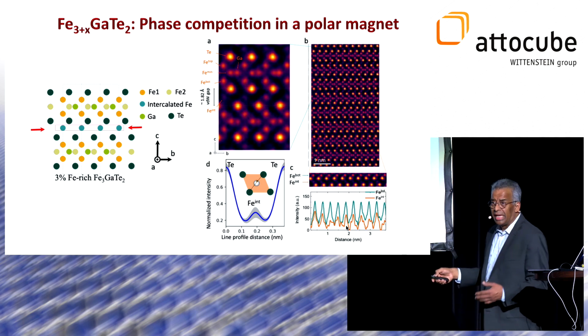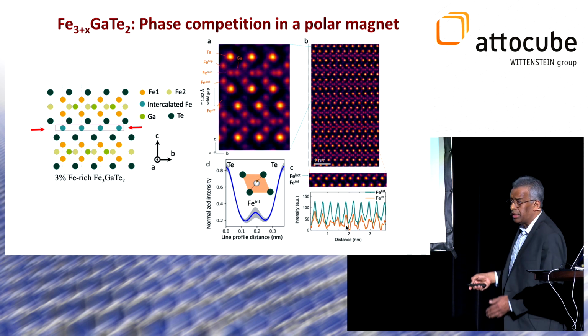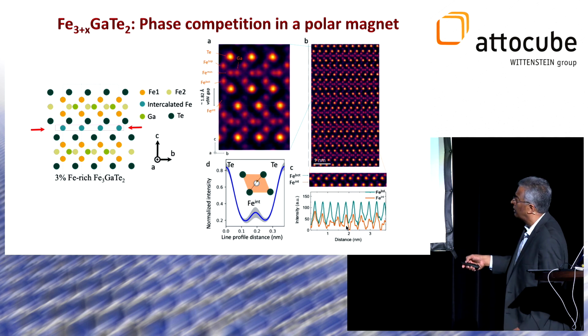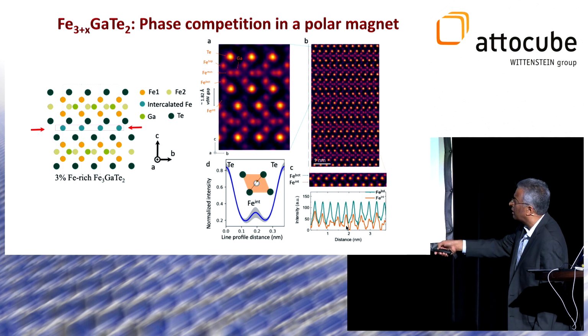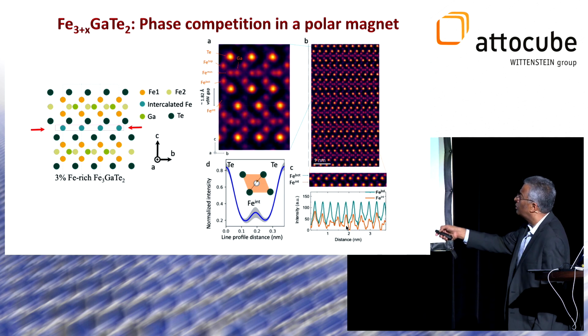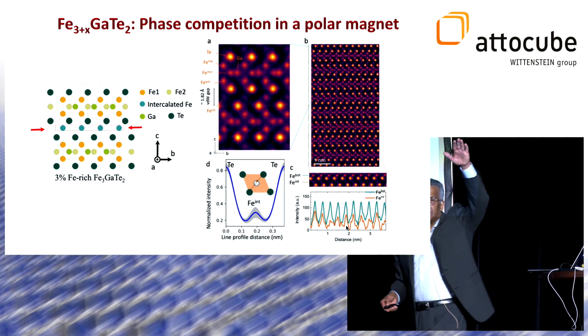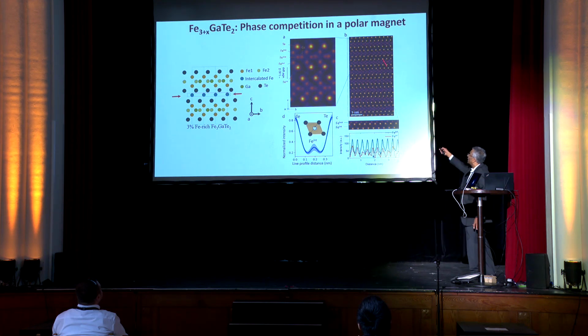That leads to, again, a very interesting magnetic state. There is competition between multiple phases. You can follow that intercalated site quite easily through these images. Keep in mind that these images are projected through the thickness of the sample, which is maybe 10, 20 nanometers or so. Okay? And these are the bigger scale images of the atomic structure.